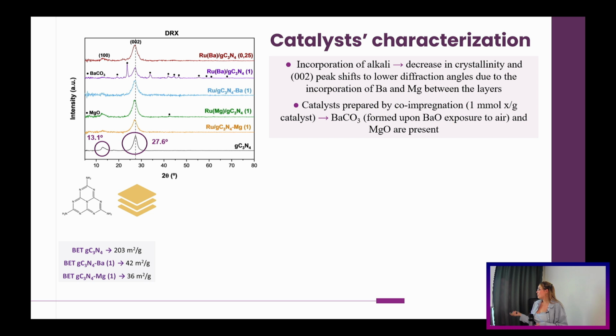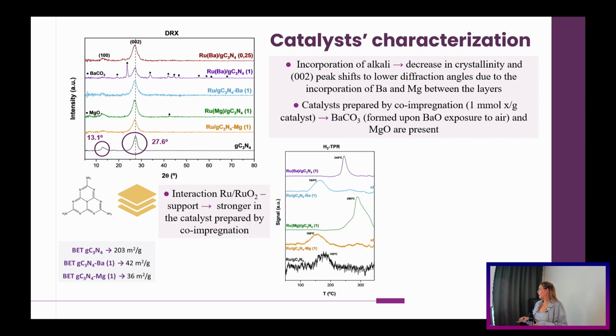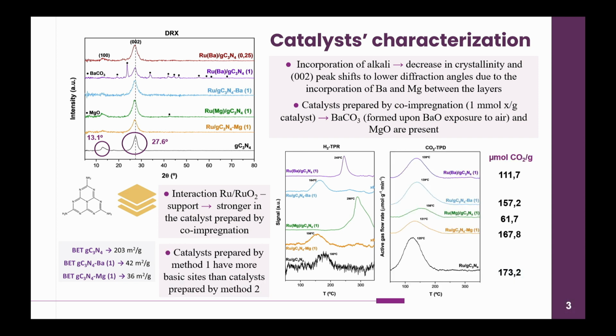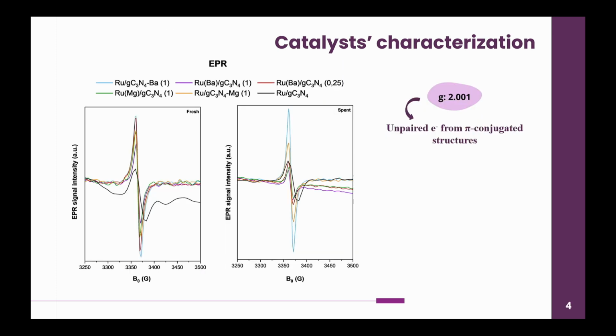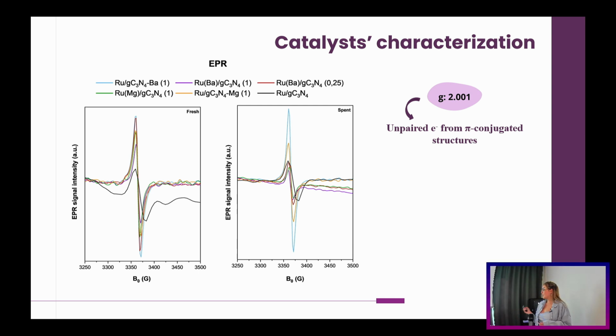These are the BET results, and in hydrogen TPR, we observe that the ruthenium-support interaction is stronger in the catalyst prepared by co-impregnation. Then in CO2 TPD, we see that the catalyst prepared by mixing the alkali and the urea before the thermal polymerization has more basic sites than the catalyst prepared by co-impregnation. In electron paramagnetic resonance, we obtain this Lorentzian line centered at g 2.001, which is attributed to the presence of unpaired electrons on carbon atoms within aromatic systems.